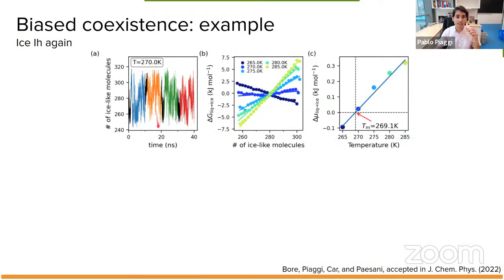Once the simulations are converged, we can compute the free energy as a function of the number of ice-like molecules for different temperatures. We clearly see here how the free energy profiles are quite linear, and the slope changes very significantly with temperature. When the slope is zero, that's the coexistence temperature. We can plot the slopes, which are the chemical potentials, as a function of temperature, and we obtain this kind of plot.